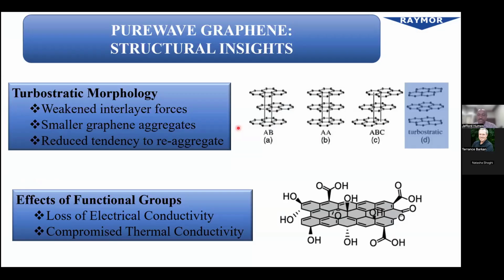So the graphene that's produced in our inductively coupled plasma reactor is very unique. Now, typically, graphene has a type of alignment between its layers, either AB, AA, or ABC alignment. What makes the graphene that we produce unique is that it has what's called a turbostratic morphology. What that means is that it leads to weakened interlayer forces, which might seem like a bad thing, but due to this layer misalignment, it allows for easier separation of our graphene sheets. The smaller graphene aggregates that are produced make this material easier to disperse, and the reduced tendency to reaggregate leads to more stable dispersions.